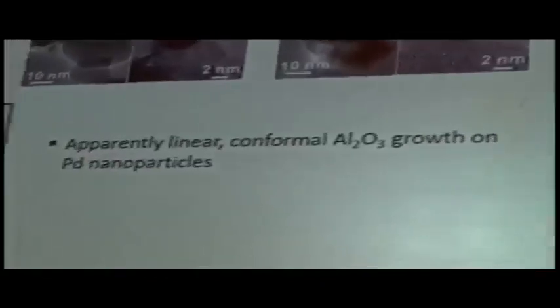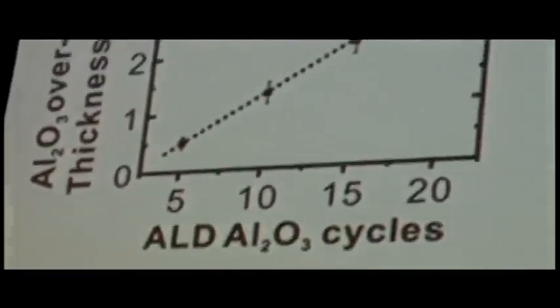As we start adding five cycles of alumina, you can start to see the formation of the alumina overcoat going over the top of the palladium particle, not changing the size of that. And as we increase that, we just increase the thickness of that layer. And what we find is there is a linear increase in the alumina overcoating as we go through additional ALD cycles of this material. We're not limited just to alumina for these materials.